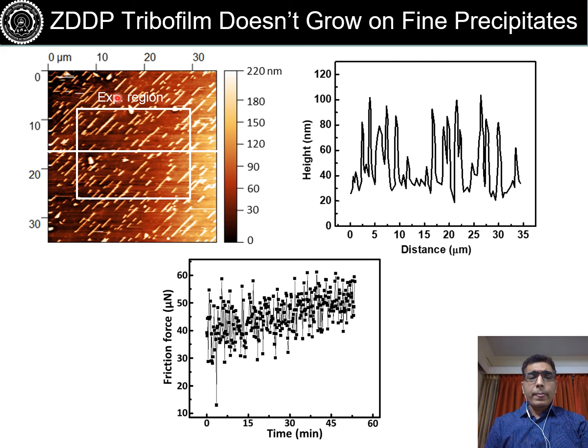But again, we did this study on a fine precipitate region, and we see that ZDDP does not form tribofilm, which suggests that these fine precipitates are not going to be good for lubricated systems where tribofilms are desired. So some microstructure tuning is required to get the right precipitate size, which does not give you poor mechanical properties but also supports tribofilm growth.